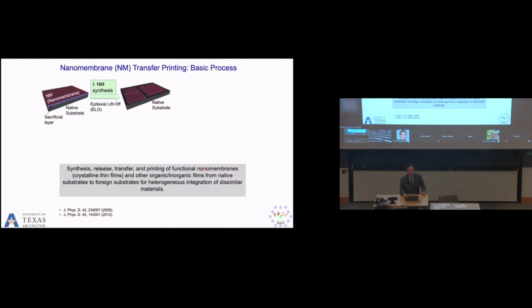So then we can release silicon. For example, on a silicon SOI platform, you can etch the buried oxide below the top silicon device layer. If you put a PDMS stamp there, it should be able to pick up this top thin layer of silicon, a few hundred nanometers, tens of nanometers, whatever thickness you want, and transfer it onto any foreign substrate. That's the flexibility here. You can do this so-called transfer printing of semiconductor thin-film crystalline structures, which we call membranes, onto any substrate.